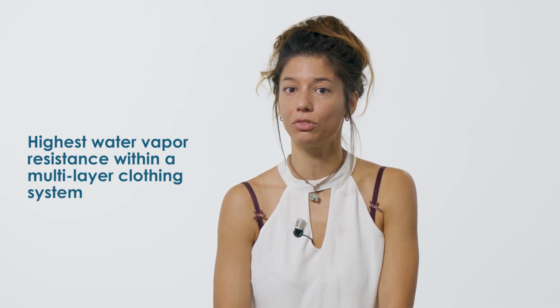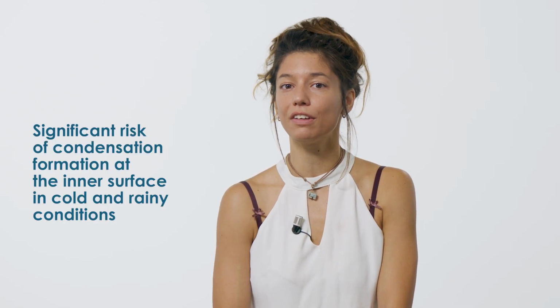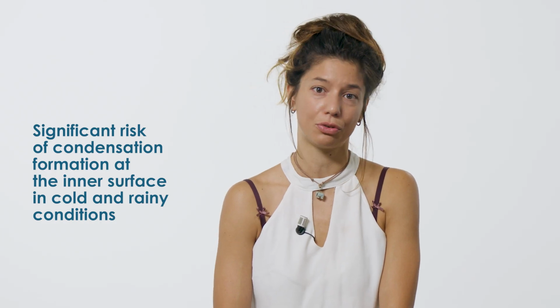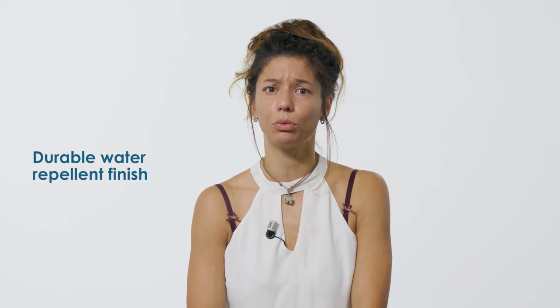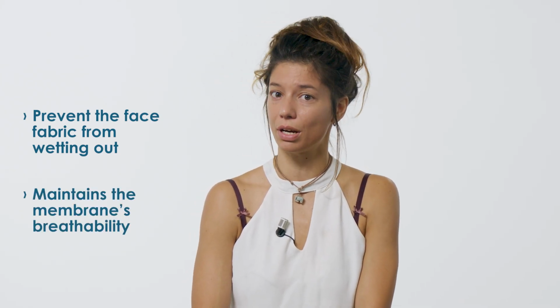The WBF layer, by its nature of providing weather protection, often has the highest water vapor resistance within a multi-layer clothing system. This characteristic, while crucial for protection, introduces a significant risk of condensation formation at the inner surface in cold and rainy conditions. The higher the water vapor resistance, the greater the condensation risk. Furthermore, in rainy conditions, the overall water vapor permeability of the garment can be impaired if the outer shell itself absorbs water. For this critical reason, it is common that the outer shell layer is treated with a durable water-repellent finish, which helps prevent the outer fabric from wetting out and thus maintains the membrane's breathability.